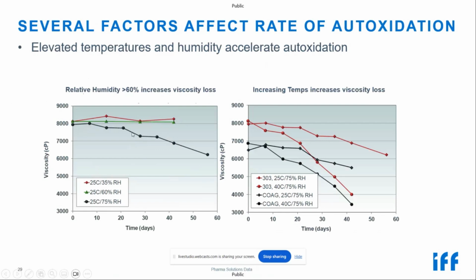When we raised that relative humidity to 75%, we saw a drastic increase in the viscosity loss over that same time. In the same study, we were testing the impact of temperature on the viscosity loss. So these are two different grades of PEO. We have the high molecular weight 303 up here in red, and still a high molecular weight, but just one grade lower, coag, here in the dark blue or black lines. With the diamond shapes, those were stored at 25C, 75% relative humidity, not a great choice for relative humidity, but we kept relative humidity constant for all of these samples.